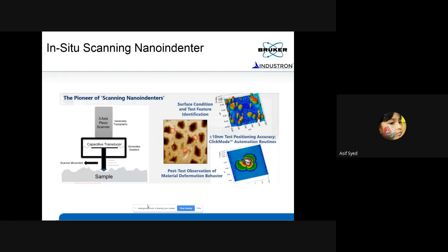Here in this slide, I'm showing on the right side that you can see the images. The first image is of a wood cell. You can see the cellulose structures, and you can clearly see the cell wall. And you can see in the rounded, like in red markers that I have put, small dots. Those dots are basically indents that have been placed all along the cell wall boundary.